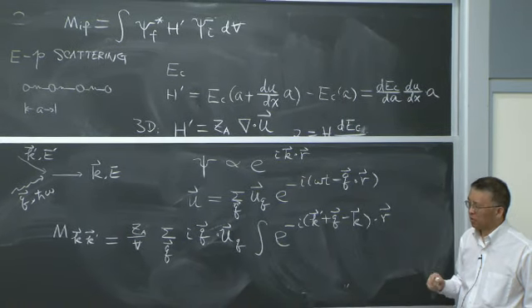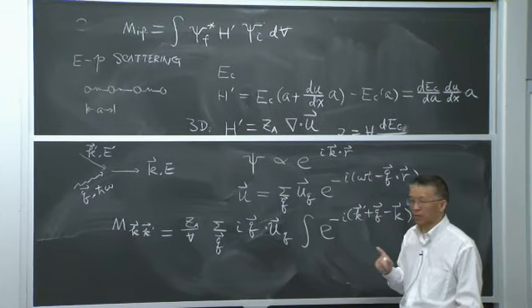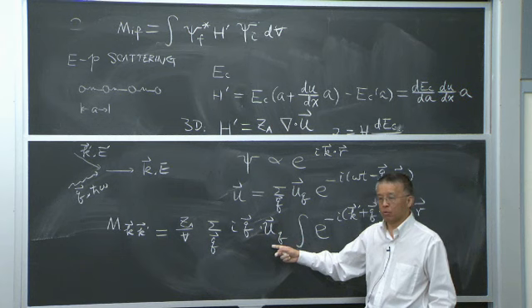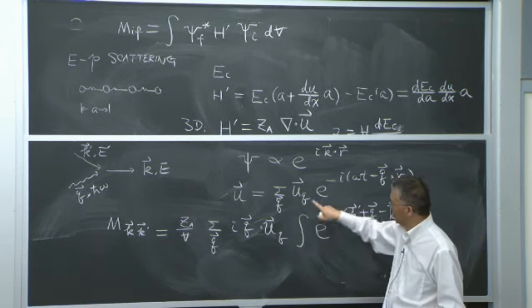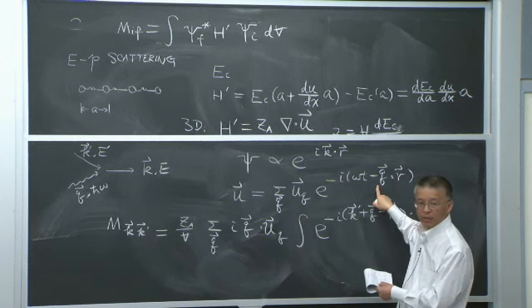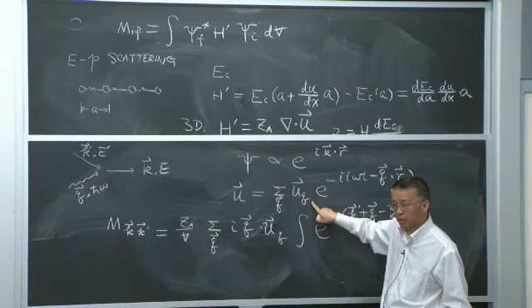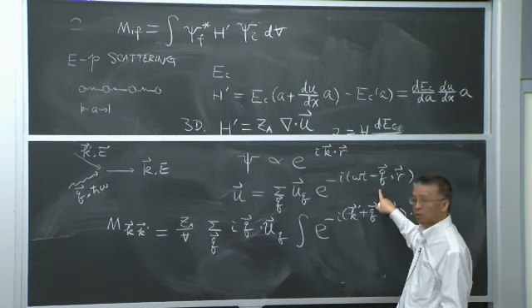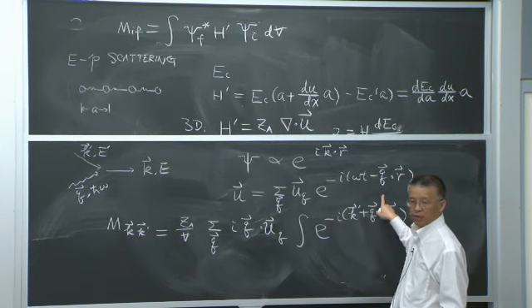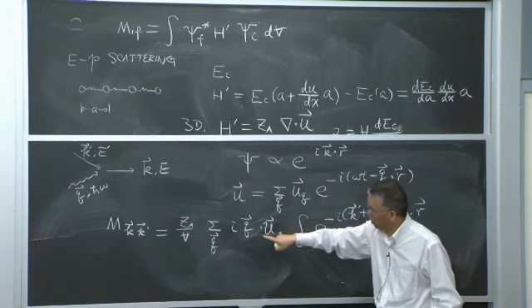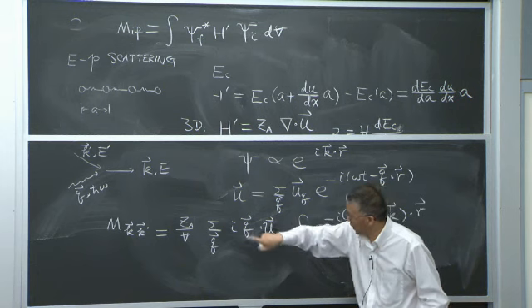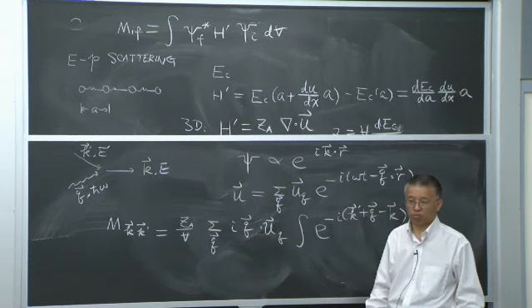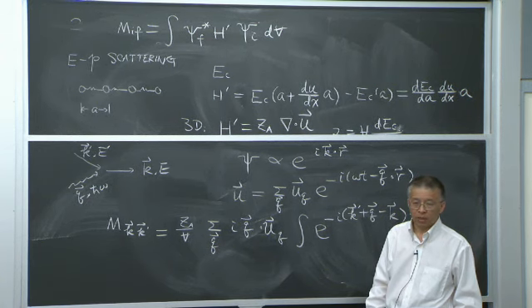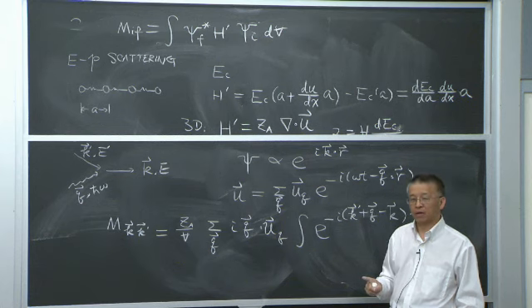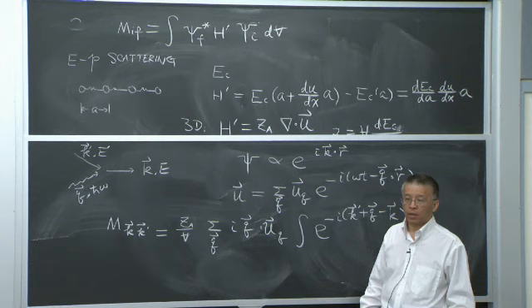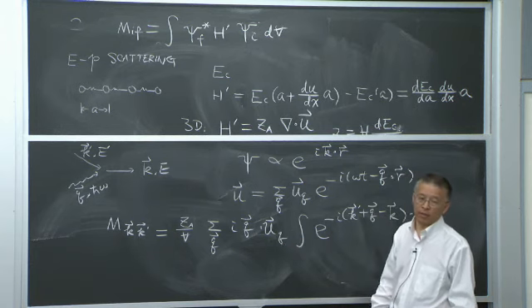So the point I want to make is, if you look at this expression, what really scatters the electron? u_q. For the phonon, this is the plane wave, q is the phonon wave vector, the phonon propagation direction, and u is the lattice displacement direction. Whether it's a transverse wave, if it's perpendicular to q, or a longitudinal wave, if it's in the same direction as q. Because of this deformation potential, in the end my scattering matrix is the dot product of q times u. That immediately tells you the transverse phonons do not scatter electrons, because this is zero, and it's the longitudinal phonon that will scatter electrons. That's one.